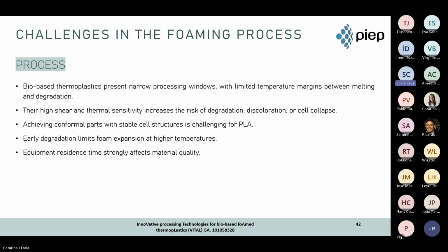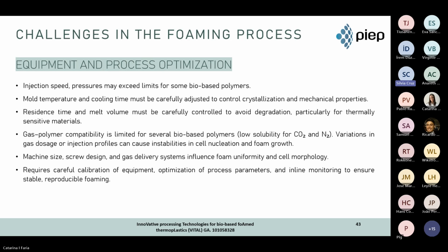Regarding the process, I've more or less talked about it on the previous slide, so I'll go through this slide to the next one. So regarding equipment and process optimization, injection speed and pressure may exceed limits for some bio-based polymers. Mold temperature and cooling time must be carefully adjusted to control crystallization and mechanical properties. Residence time and melt volume must be carefully controlled to avoid degradation, particularly for thermosensitive materials.